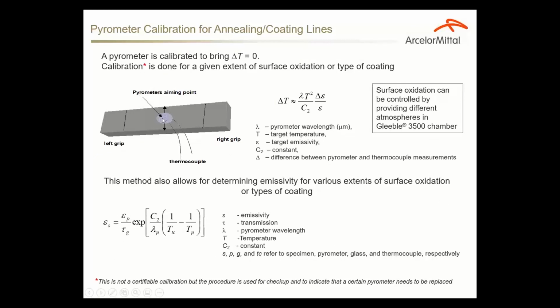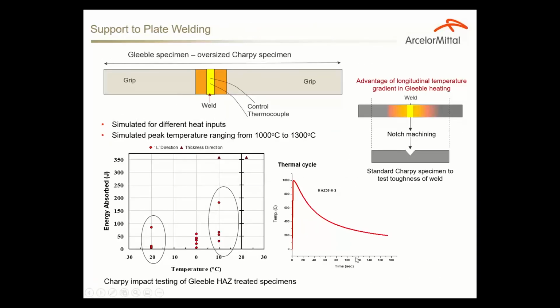We aim the pyrometer on one side, we weld the thermocouple on the other side of the strip, calculate the delta temperature, calculate emissivity, and we can calibrate the pyrometer. This is, of course, not a certifiable calibration, but the mills bring the pyrometers here to check whether they're good or not, whether they need to be replaced or not, and so forth.